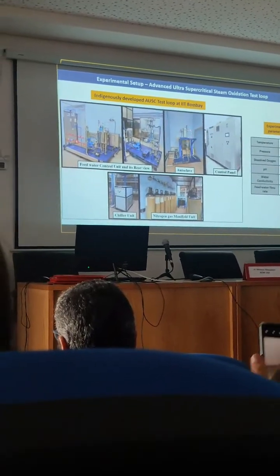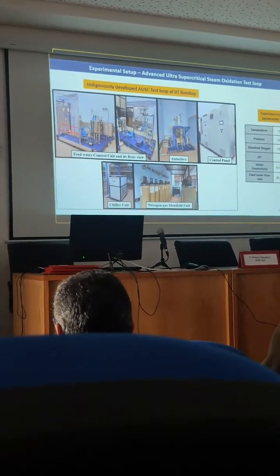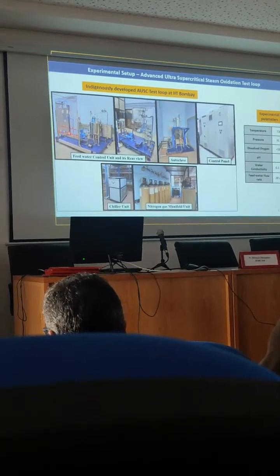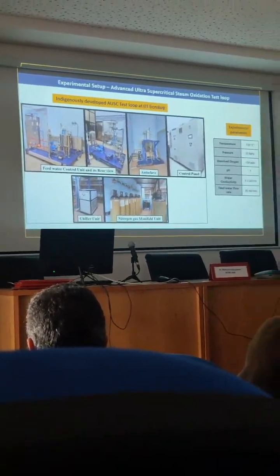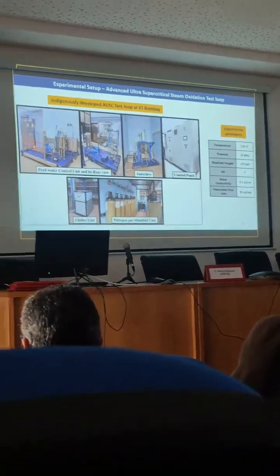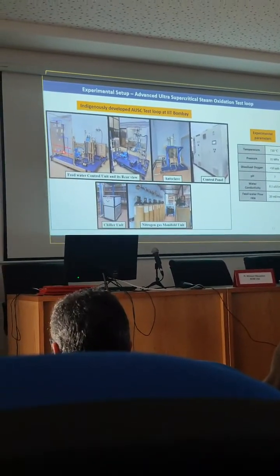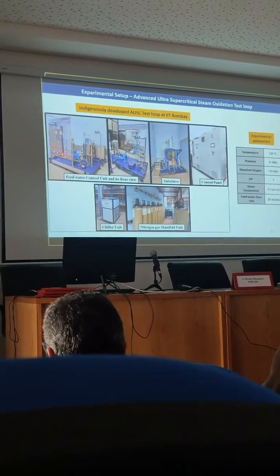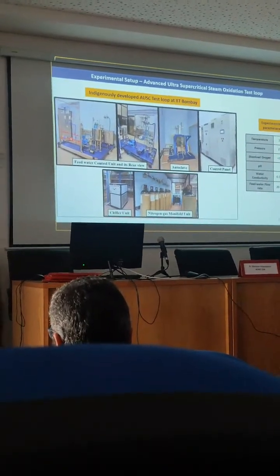So you have the autoclave system. You have water treatment. Water treatment is important. You can't use normal water. The conductivity of the water is 0.1 microsiemens. You see here, 0.1 microsiemens water. The oxygen content is very low, 10 ppb. So all the systems are here. This is called